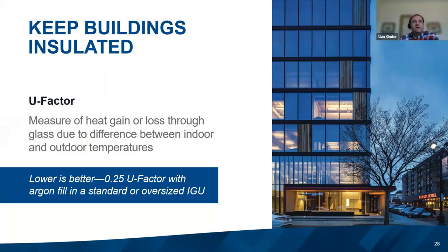So we do express U value as a decimal number. The lower the decimal number, the better that glass does in terms of retaining that warm air in colder climate months. Typically what we find with most low E coatings in a 1-inch insulating glass unit with an air-filled cavity is going to be in a range of a 0.28 to about a 0.32 U value.